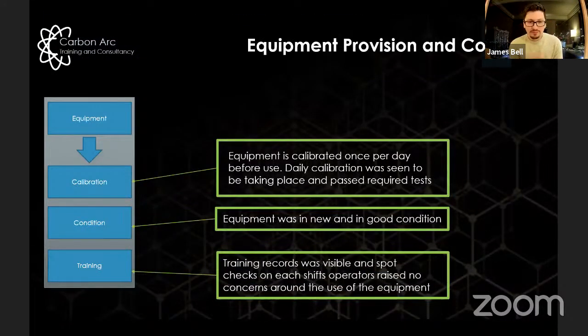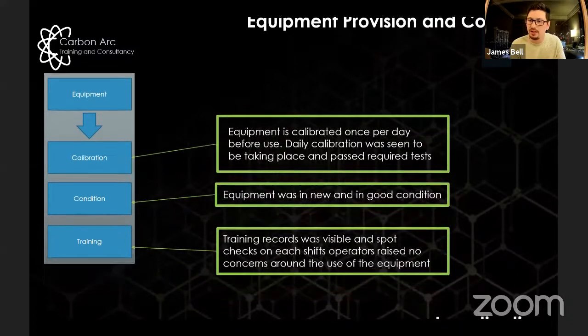So then we started looking at the equipment. Is the Fischer Feritscope in calibration? Yes, it is. Is it in good condition? Because we all know what happens with equipment when you give it to somebody on a work site. It normally doesn't last very long, but no, the condition was new. It was how it was operating. All our tests on the calibration blocks said, yes, this is all okay. And then we did spot checks on the training of all of the operators globally and found that everybody knew exactly how to use the equipment. We could take them through a blind test on calibrating and taking test results, recording test results. We even went to the extreme where we checked that they were able to average 3 result numbers correctly, because we just couldn't work this out. And again, everything was green, everything was fine.